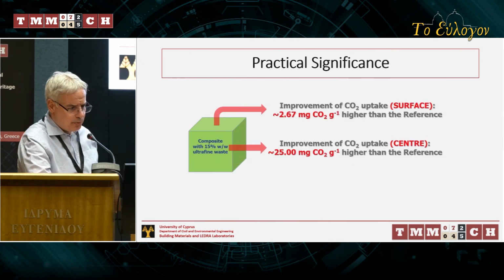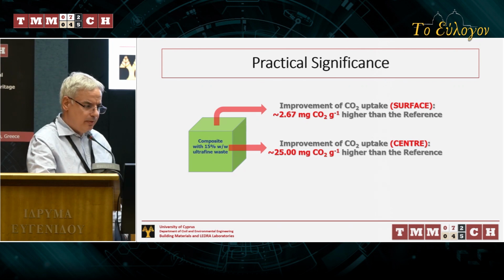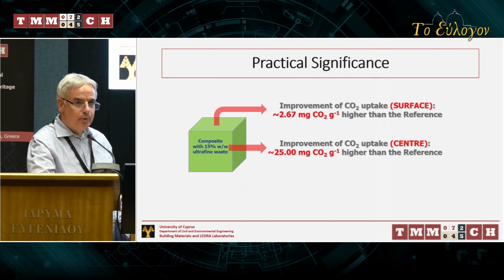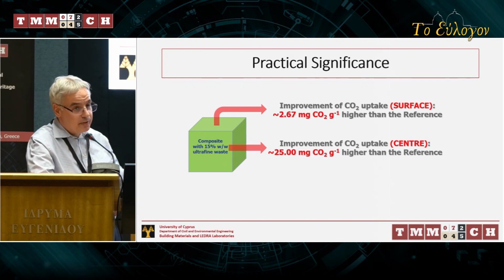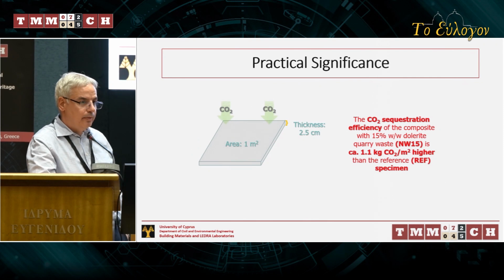Practically, this corresponded to an improvement in CO2 uptake in the center of the sample with the waste additive of approximately 25 milligrams per gram, compared to a mere 2.5 milligrams of CO2 per gram at the surface of the same sample. And if we want to translate this into CO2 sequestration, we can say that this is roughly equivalent to an extra 1 kilogram of CO2 per square meter of render, supposing that the thickness of the applied render would be about 2.5 centimeters. And this is again compared to the reference sample.